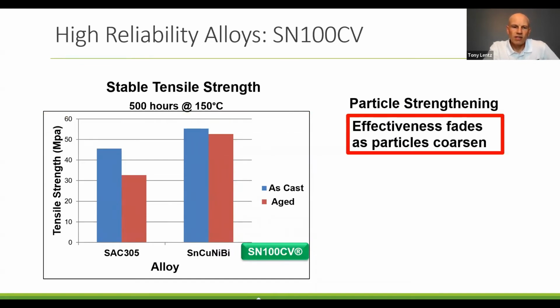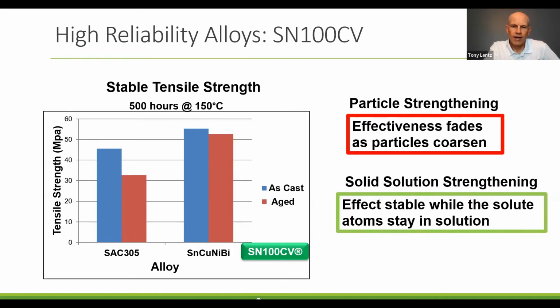And that's because SAC305 depends upon solid particles, intermetallics of silver, copper in that alloy that get coarser over time. They grow in size, they agglomerate together, and that coarsening effect makes it lose tensile strength. Whereas SN100CV has an amount of bismuth chosen to remain in solid solution, and it's uniformly distributed throughout the solder so that it has very stable strengthening effect even after aging.